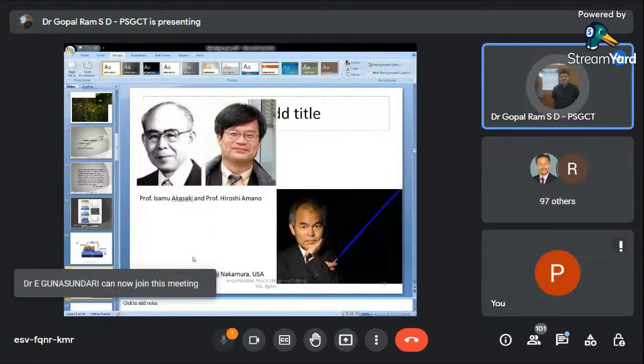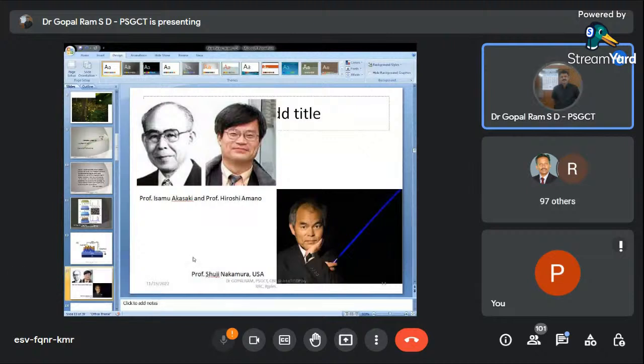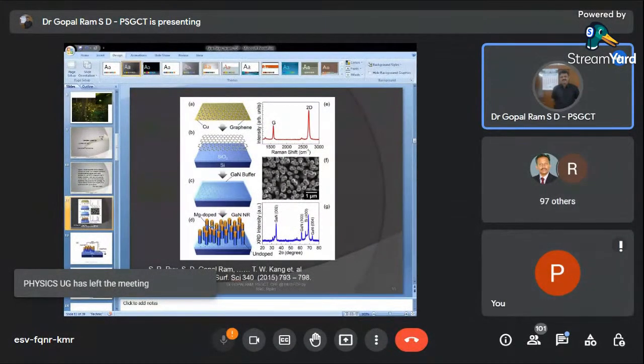What does the name convey? Metal organic chemical vapor deposition. Deposition, we are able to understand, is vapor deposition, where that vapor is produced from a chemical reaction. And what is the metal organic? These days you can see CVD, chemical vapor deposition, in many places. So if you supply the metal in the form of metal organic vapor, for example, ethyl gallium or methyl gallium, something like that. If you want to mix the dopant with the gallium nitride, magnesium will be mixed in the form of metal organic vapors, right? So that much high quality, controlled flow of vapors was required for the preparation of this P-type gallium nitride.